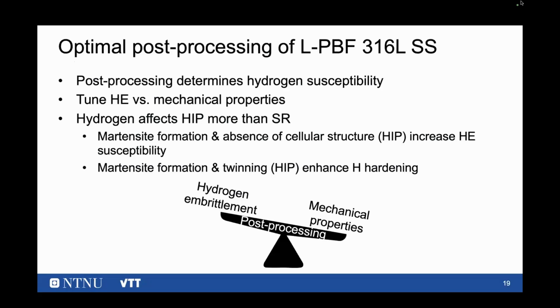So it brings me to the conclusion that, depending on the post-processing, you can really tune between good hydrogen embrittlement resistance or the mechanical properties that you want. And in this example, the stress relief condition has a higher strength and better hydrogen embrittlement resistance.